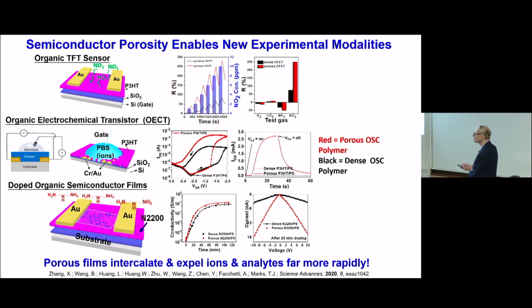So this is an electrochemical transistor. It looks like a transistor. Here's the polymer, but there's a liquid electrolyte here. And the liquid electrolyte allows ions to move in and out of the polymer. And so when I switch it on, it's not only the field effect carriers, but it's all the other carriers that we've created, turned on and off in the polymer. And so you get huge currents.